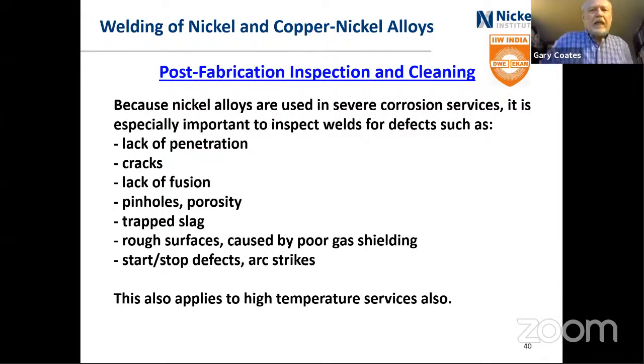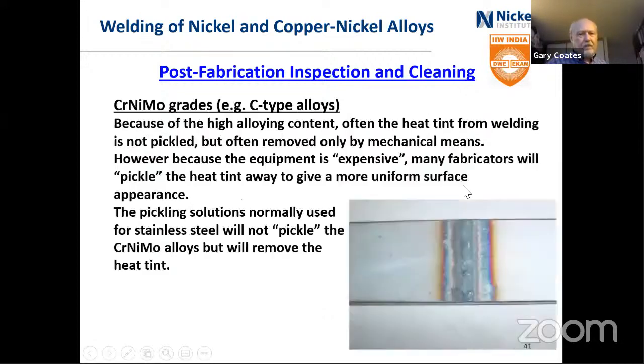Just a few words on post-fabrication inspection and cleaning. As we can imagine, with anything that's being used in severe corrosion services, you do have to look and inspect the welds carefully for any kind of defects, which may impair its function in service. They're the regular ones. Even more important than with stainless steels, to look for these and find these and correct these, because of the severe service they're going into. And this also applies to high temperature services. In high temperature, things get heated up and they expand, and then they contract as they cool down and heat up and expand again. So any type of surface defect can easily lead to cracking.